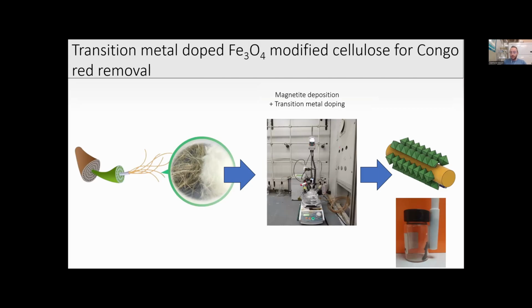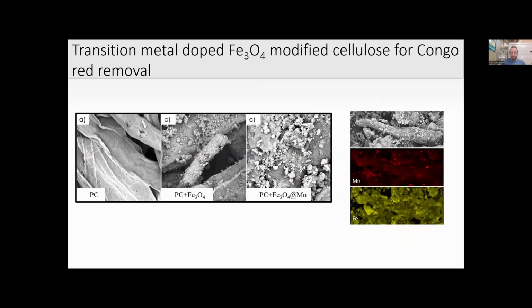In this work, cellulose derived from the rice straw was modified with magnetite, which was further doped with manganese in order to improve their magnetic properties, which can be exploited to recover this material from wastewater after their use. You can observe here the surface of pristine pulp cellulose, the pulp cellulose modified with magnetite, and one doped with manganese. Manganese was chosen in order to improve the adsorption and the magnetic properties of this adsorbent.